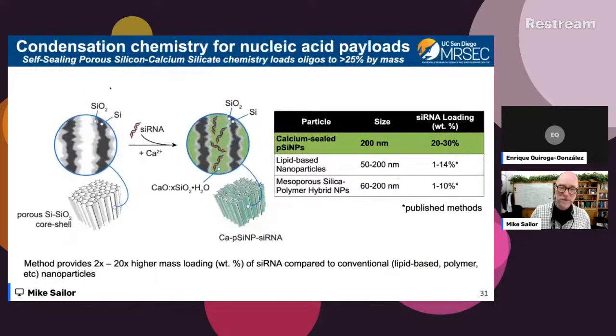And so we thought, well, let's try to use a silicon sealing chemistry that we use for our other molecule, our vancomycin, and see if the same sealing chemistry can work on a nucleic acid. And the beauty of that is that calcium ion actually has an ability to help compress and condense nucleic acids. So with this calcium ion sealing chemistry, we were quite surprised to find that it has a remarkable ability to load a lot of nucleic acid into the nanoparticle.